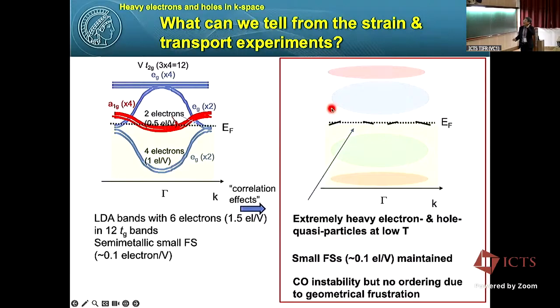So now, this is what we obtained from transport. We started from this band, and somehow we found extremely heavy, equally enhanced electron and hole at low temperature. And somehow they form a relatively small Fermi surface, 0.1 electron per vanadium. So they seem to maintain the LDA Fermi surface. Okay. Although, I have to say, because we have an even number of electrons, we don't have to satisfy Luttinger's sum rule, but somehow they respect the LDA band calculation. So the mass is as large as 100.